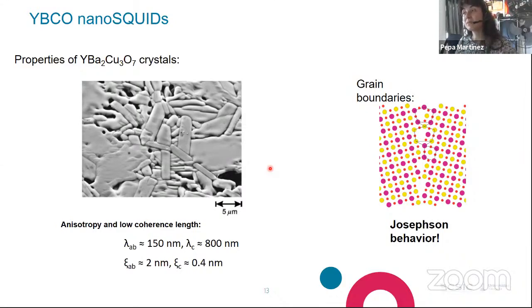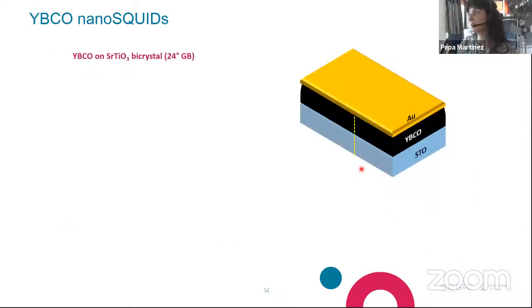The problem is that patterning very small Josephson junctions down to the nanoscale or microscale is quite difficult with these materials. These materials are very anisotropic and their transport properties depend dramatically on the quality of the crystal. That also has a nice consequence for us, and is that grain boundaries between two crystals having different orientations exhibit Josephson behavior. And that's how we fabricate our nanoSQUIDs. I will show you that in this slide.